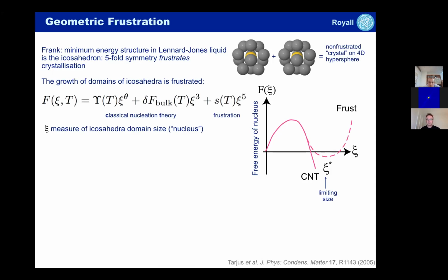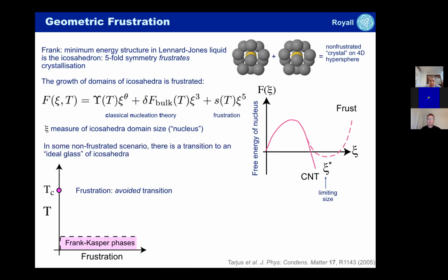But nevertheless, the idea is that the formation of these icosahedra is related to this transition to an amorphous solid glass. And the reason for that is that if we imagine that they were not frustrated, and it turns out that if we curve space, we can make effectively a crystal of icosahedra, then in curved space, there is a phase transition to this state of icosahedra, this crystal-like state, and we imagine that we are somehow close to this curved space, albeit in Euclidean space, and so this avoided transition is nevertheless controlling what is going on with the dynamics of the material and leading to the solidification. So an avoided transition to a state of icosahedra that would occur in curved space is what governs the solidification process in amorphous solids.